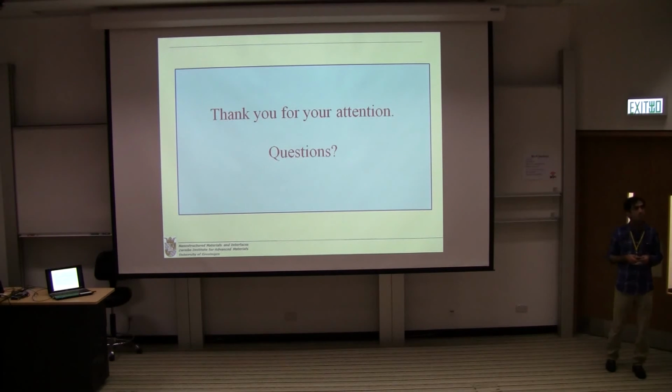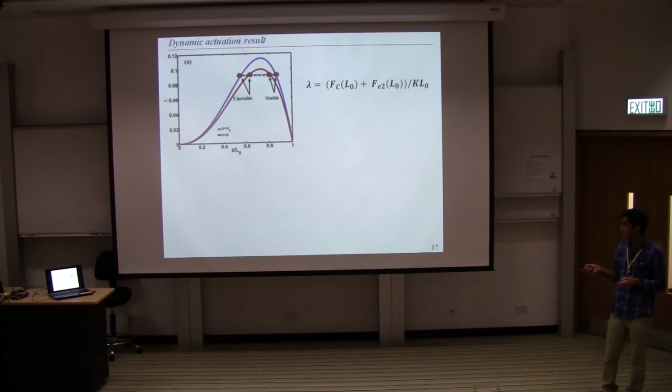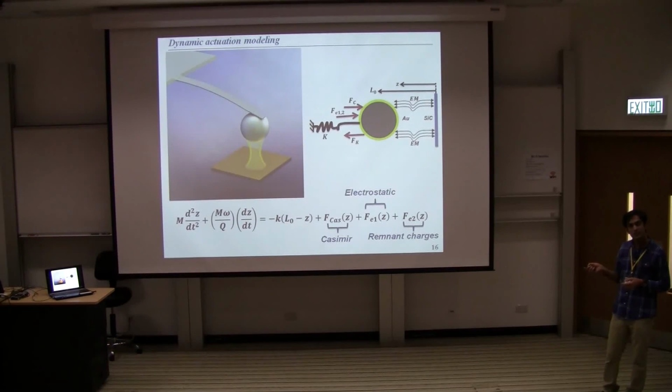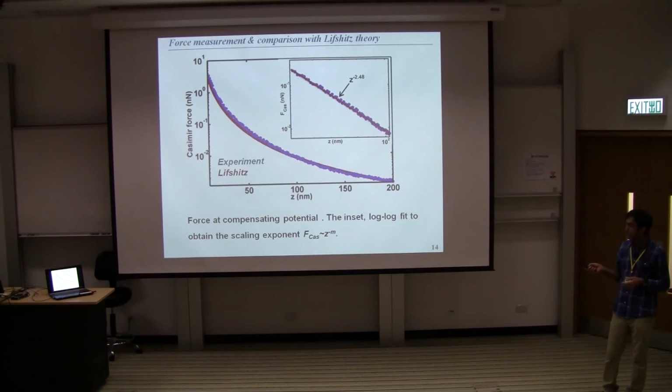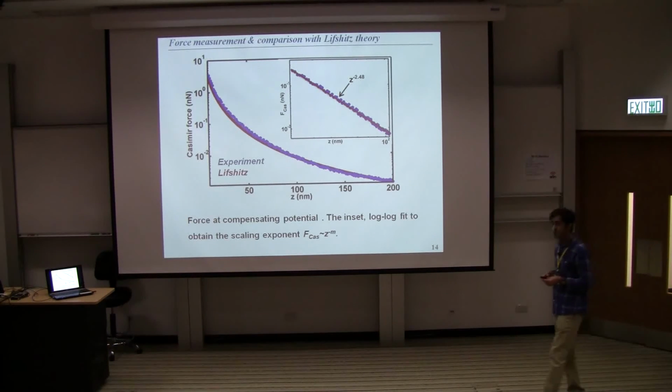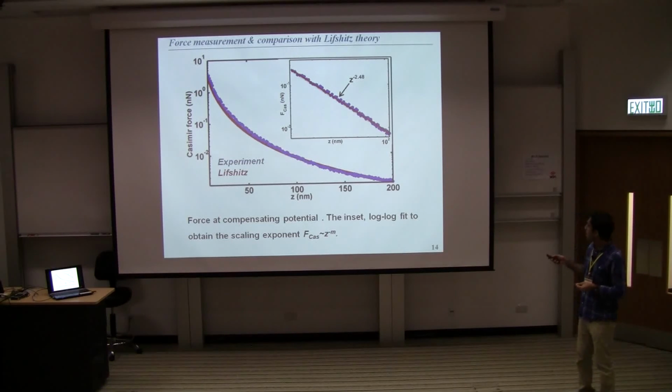You showed this logarithmic dependence in the potential, in the electrostatic force. And you also showed that the difference between the Lifshitz result and your measurements, exactly here, is approximately 30% at close distance. Have you tried compensating the electrostatic force dynamically by measuring the second derivative using an SE potential? Because then you could basically get this to zero. We have done that in experiments.